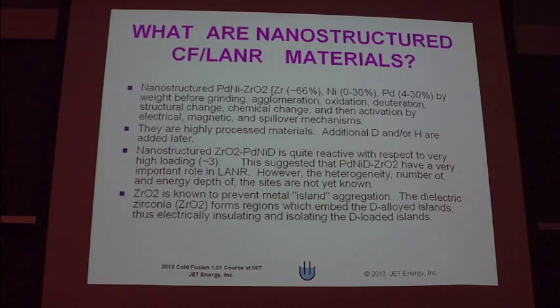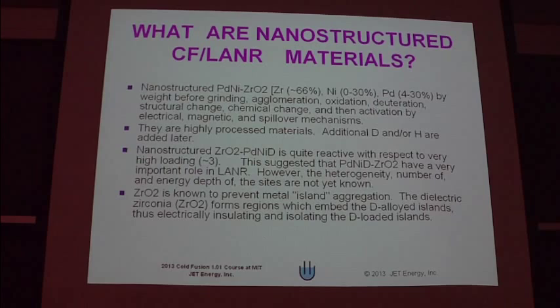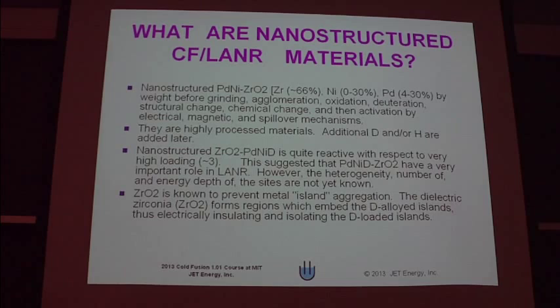We further process it — we add the deuterium. The interesting things about these nanostructured materials are: one, you get very high loading by calculation. We're getting net loadings that are three or greater compared to the palladium alone. It's heroic to get up to 1.2 or 1.3 in the conventional system; here it's quite easy to get the high numbers. But it might be that we're having areas within the nanostructure that's not active, so when we see three it may not be all within the active material.